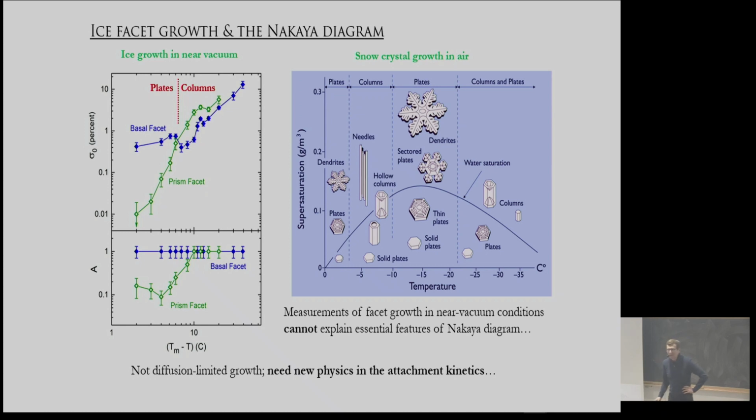Yeah. It's low enough that the diffusion correction is pretty small. And so if you grow in air, you've got to worry about the difference between the supersaturation where you make it and at the crystal surface. And it's a huge correction at 1 bar. And it starts to be tolerable at some millibars. So we can do that, okay?